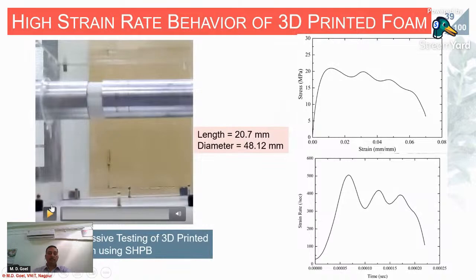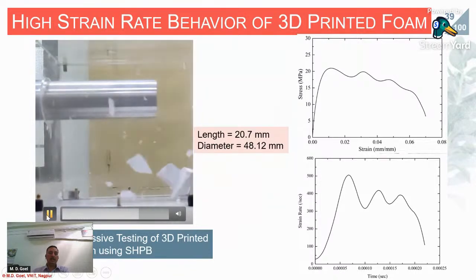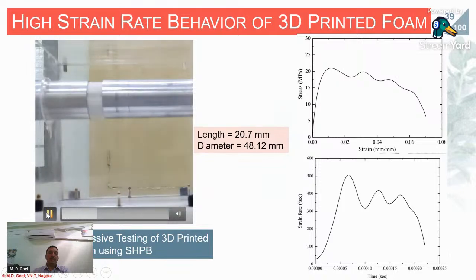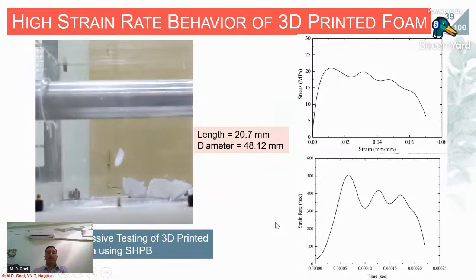This is a typical test carried out at VNIT Nagpur on a 3D printed foam. One of our collaborators sent us the 3D printed foam, and we did the test at a strain rate of around 400 per second. Its quasi-static strength was very low, around 5 to 10 MPa. Once it is subjected to a strain rate of 400 per second, the strength achieved is around 20 MPa. Let us see how it is behaving. You can see the sample is getting completely crushed, and using the incident and transmitter bar, we get the stress strain curve of the material.